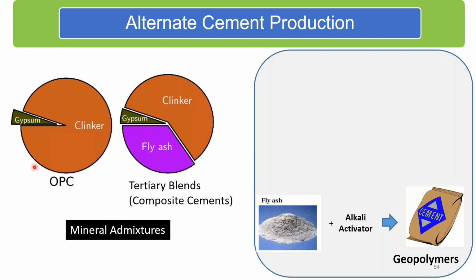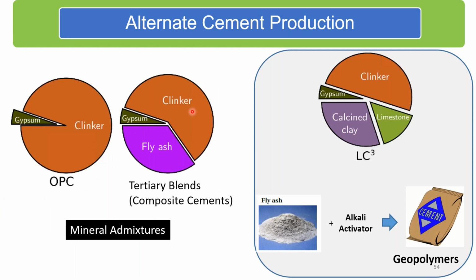Now, we've looked at the ternary and binary blends, where we are looking at clinker substitution with fly ash. There are other cements that are also being produced. One of them is the LC3 cement, where we bring in calcined clay and limestone as a substitute for clinker. And with this, we are able to achieve about 50% clinker substitution with calcined clay. And the calcined clay itself doesn't have to be very high grade clay. And so potentially there are savings here with this material. Now, the other way of looking at materials is to look at alternate cement chemistry, which does not start with limestone.